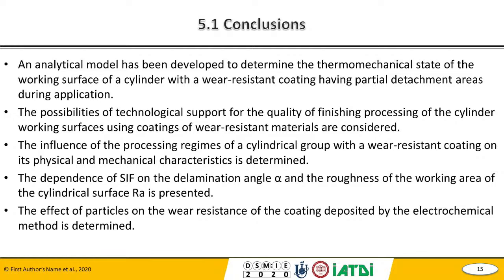Short conclusions. An analytical model has been developed to determine the thermomechanical state of the working surface of a cylinder with a wear-resistant coating, having partial detachment areas during application. The possibilities of technological support for the quality of finishing processing of the cylinder working surfaces using coating of wear-resistant materials are considered. The influence of cylindrical group processing regimes with wear-resistant coatings on its physical and mechanical characteristics is determined. The dependence of the stress intensity factor on the delamination angle alpha and the roughness of the working area of the cylindrical surface is presented. The effect of particles on the wear resistance of the coating deposited by electrochemical methods is determined.